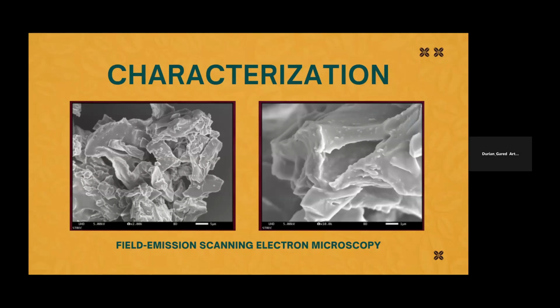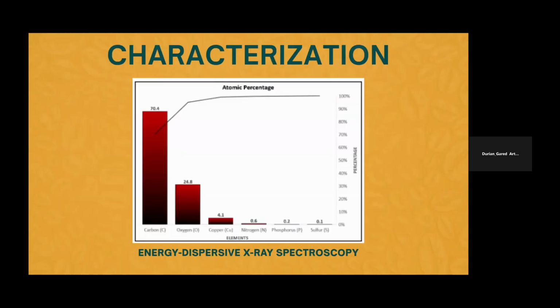So at the 5 micrometer scale, the image shows a cluster of layered sheet-like graphitic structure, which is characteristic of graphene oxide. Then moving to the 1 micrometer scale, more defined, wrinkled surfaces can be seen with the sheets, indicative of graphene oxide's tendency to form after the synthesis process.